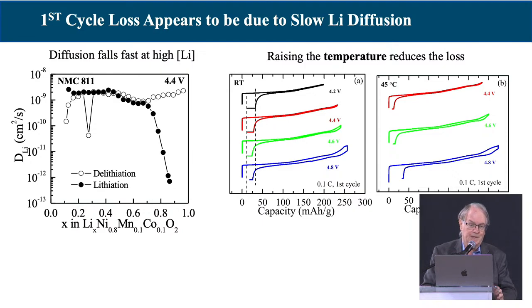To convince ourselves that that was indeed the case, first we charged to different voltages. We knew going to higher and higher voltage would get better capacity, but you still see this first cycle loss. And I should point out what we typically do is discharge to 2.8 volts. If you hold it there, you get more lithium in. It's telling you straight away it's a kinetic issue. The other point to make here is when you get to 4.8 volts, you now see the charge-discharge curves are separated, which means our material is reacting with that electrolyte. So the system is falling apart.